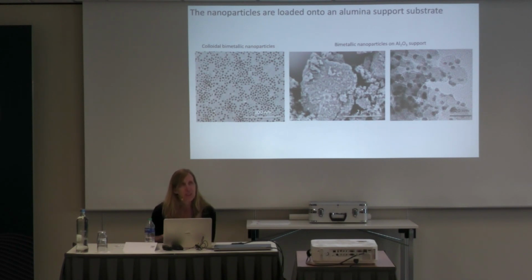Basically, I wouldn't say the hydrogenation versus dehydrogenation is faster or slower. Whichever of those processes you're looking at, it's roughly about the same period of time for each, but it's always faster with the light on. The examples I showed you are light on with hydrogenation versus dehydrogenation. So the light is what is expediting the reaction. In all cases we cycle the system 3 times with hydrogen to make sure that any lattice imperfections during the colloidal synthesis have relaxed. We usually find that the results, once you've cycled it 3 times in the TEM, are very consistent.